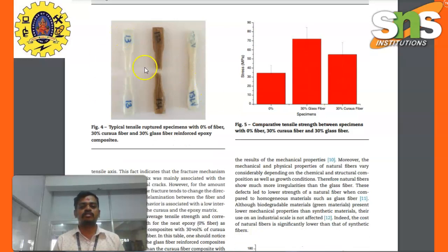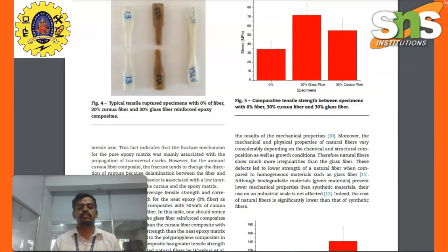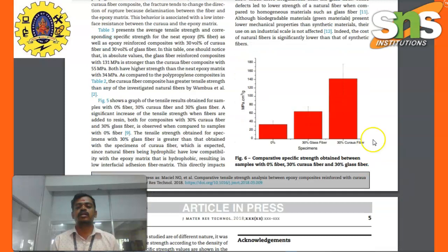These are examples of typical tensile ruptured specimens with 0% fiber, 30% curaua fibers, and 30% glass fibers reinforced epoxy composites. These are the comparative tensile strengths between the specimens of 0%, 30% curaua, and 30% glass fibers. A comparison of the specific strength obtained between the samples with 0%, 30% curaua fibers, and 30% glass fiber.